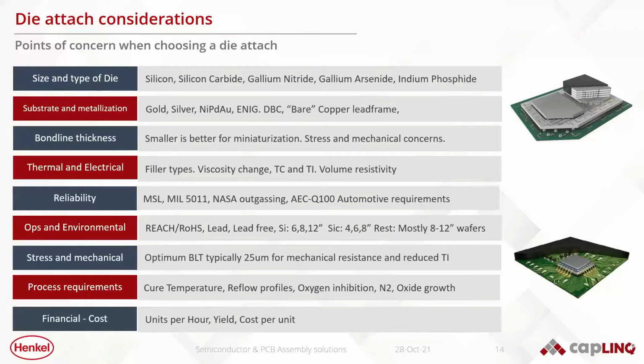Bond line thickness: the trend in these packages is to go thinner and thinner and thinner for miniaturization. But as you go thinner, that leaves less die attach material to take up the stress within the package. Ideally you would say, give me the highest bond line thickness that I can, but as you're trying to shrink that down, you're going to go for a thinner bond line, which means that you might want to consider materials that have a lower stress or maybe a lower modulus for those applications.